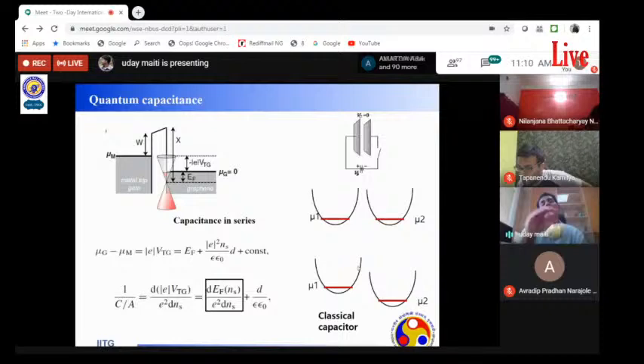Voltage, what will happen? So the mu, that means the chemical potential of one will go higher and the chemical potential of the other will go lower. But due to their high density of states, the electronic level will not change. It is similar to the fact that suppose you have two buckets of water, and if you take 100 ml of water from one bucket to another bucket, the water level will not change. This is like a classical capacitor. Only the height of the bucket matters.